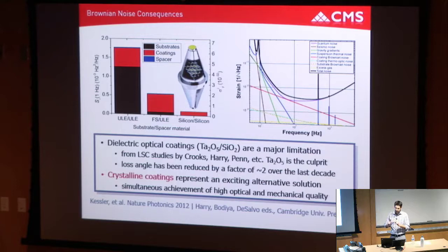It just turns out that these thin film sputtered systems are not perfect glasses. I won't go into the details of how this works, but you can satisfy a bond condition, but you have multiple potential wells for positions that the atoms can sit at, and they'll basically suck up some acoustic energy in the structure there.